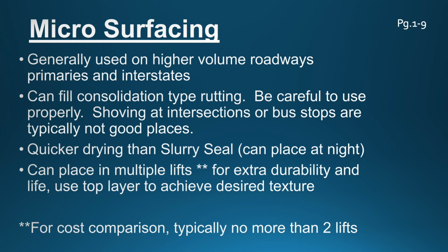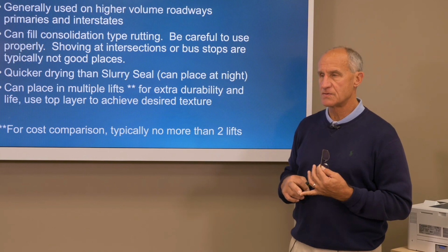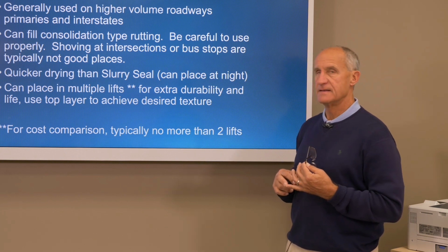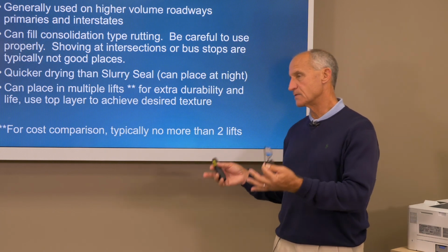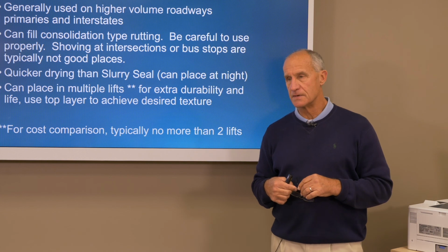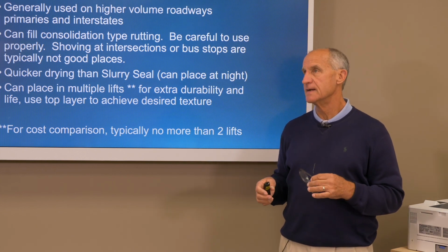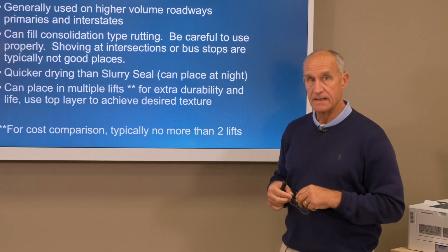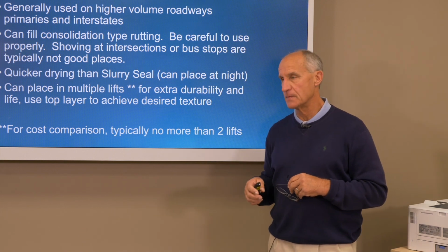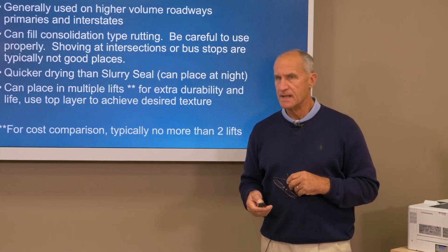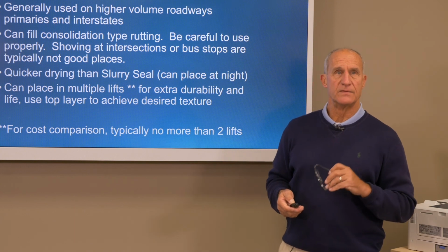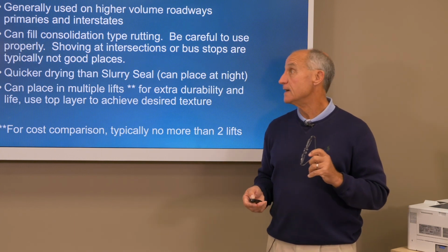What I wanted to clarify and qualify on that one is that even though, yes, you can lay the microsurfacing in multiple lifts, you've got to be careful cost-wise in that once you get beyond 2 layers of microsurfacing, you're probably into the cost range of a hot mix overlay without gaining any significant benefit from more layers of microsurfacing. So just be mindful of what the limits of this material are and what it's designed to do.